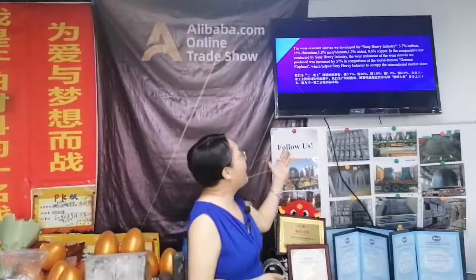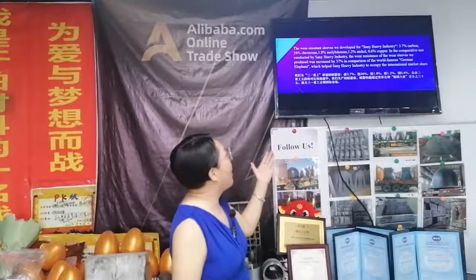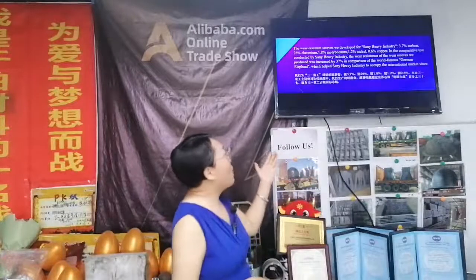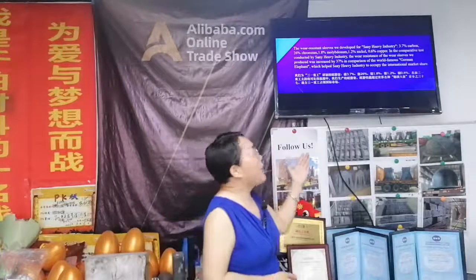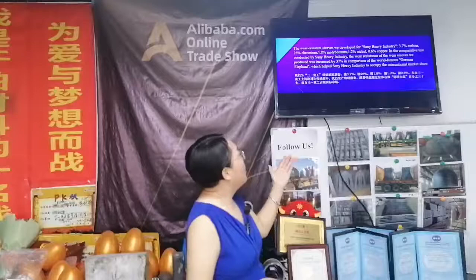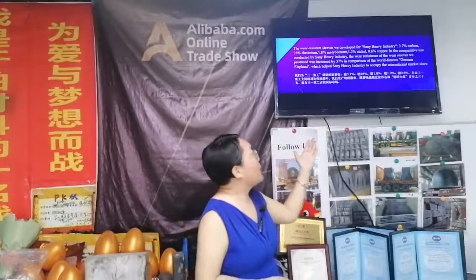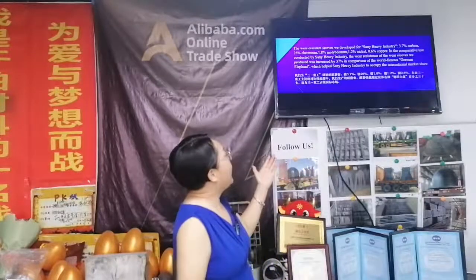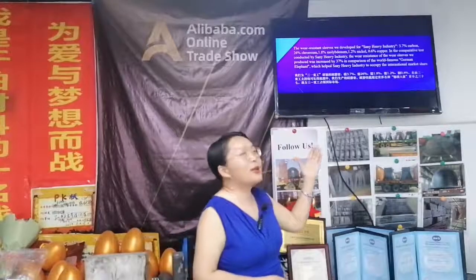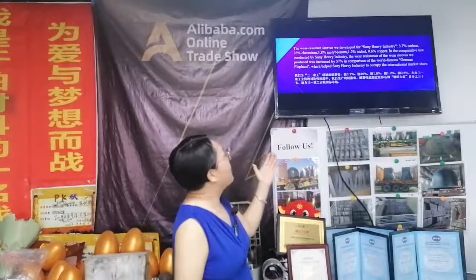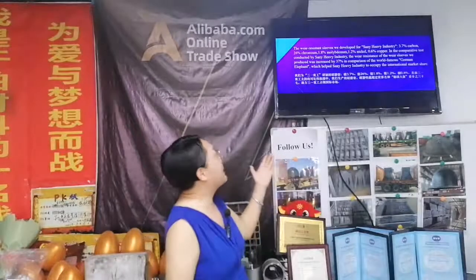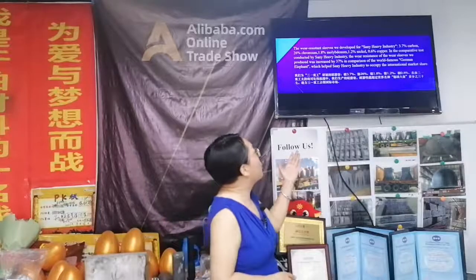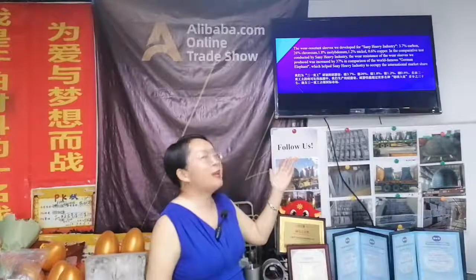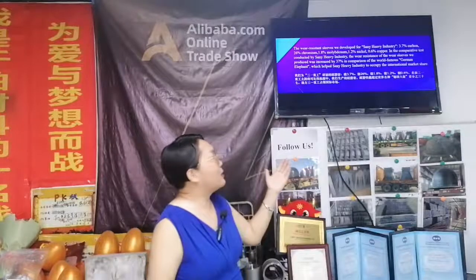So the wear-resistant sleeves we produced for Sany Heavy Industry have 1.7% carbon, 26% chromium, 1.8% moly, 1.2% nickel, 0.6% copper. In the comparative test conducted by Sany Heavy Industry, the wear resistance of the wear sleeves we produced was increased by 37% in comparison with the world famous German ones, which helped the Sany Heavy Industry to occupy the international market share.